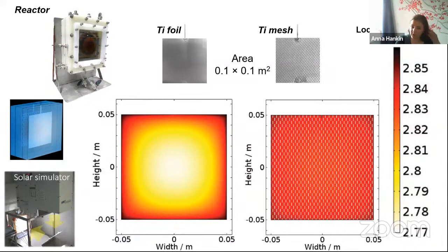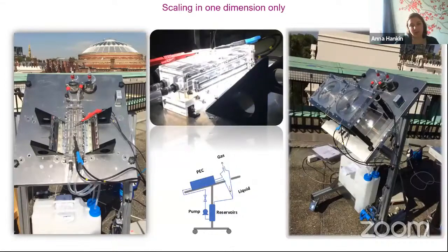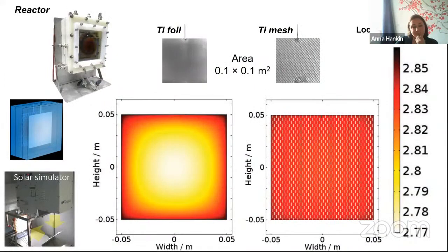Now, this demonstrated the engineering considerations, that they are in fact important, although I would stress that this perforation isn't really a suggestion that all the electrodes should be perforated. It's not really the case, because often you have several layers of material with more corrosion susceptible materials in there somewhere. And obviously if you do perforations, then everything would just corrode. But it just goes to show that the effects that I'm talking about are genuine. And we were able to reconcile the model results with experimental data.